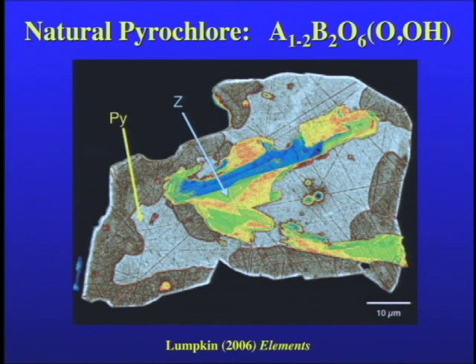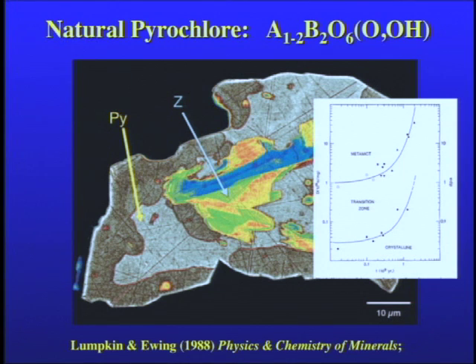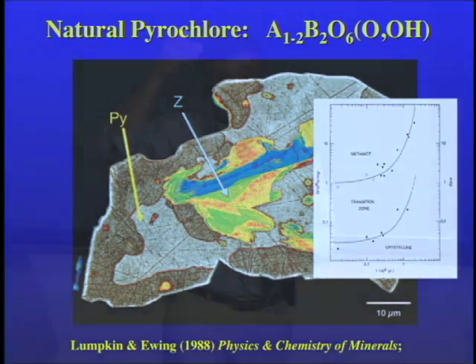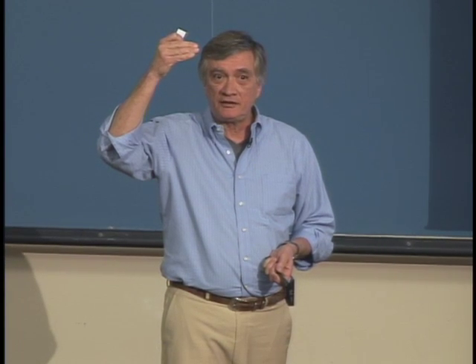In this case, the pyrochlore had 30 weight% uranium and was 100 million years old, so it was completely amorphous. And by studying suites of pyrochlore, remember this is the dose and this is the age of the samples. Remember, you go crystalline, you have a transition zone, and then finally the material becomes metamict. But looking at natural samples, what we found was that for very old samples, you had to go to higher and higher doses to make things amorphous. And that's because they were recrystallizing, they were annealing.